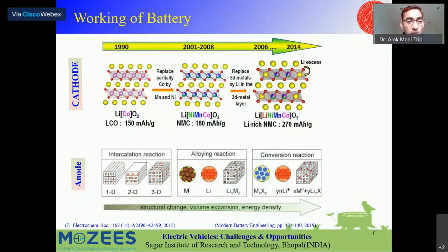So here I have shown some crystal structures. Basically, these circular things are the atoms in different colors. So this is showing different kinds of atoms in their unit cell or crystal lattice. Here is the example of lithium cobalt oxide, where the lithium lies in between the cobalt oxide channels. Then cobalt was partly replaced by manganese and nickel in 2008. And then further, what impact did we get out of this?